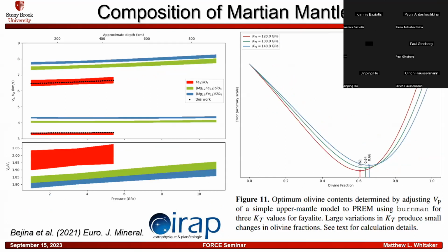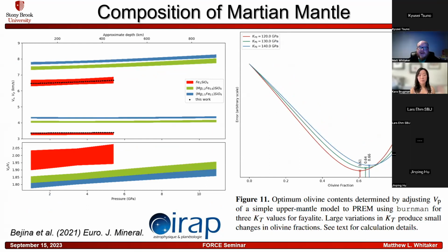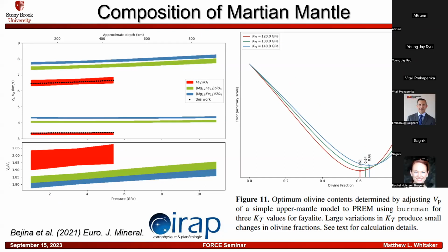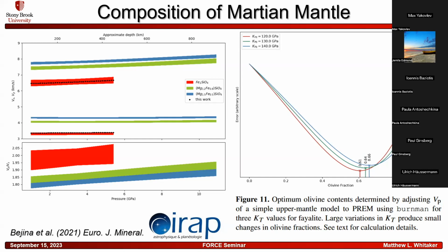And we were then able to take some of this data and use it to determine something about the composition of the Martian mantle. And what we found here is that the optimum olivine contents that are determined by adjusting the P-wave velocity of a Martian mantle model leads to a roughly 0.6 to 0.66 component of olivine in the Martian mantle. So this is an exciting application of this system.